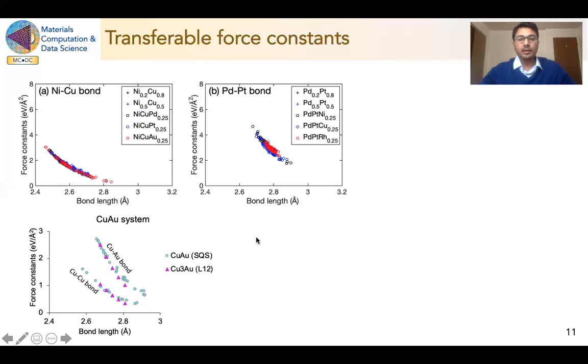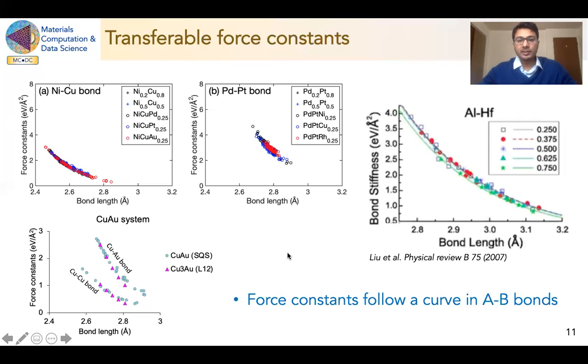Similarly, if we compare the force constants in ordered versus random alloys, again the force constants follow the same curve. As you can see in these two types of bonds, the copper-gold bond and the copper-copper bond in the copper-gold system, the force constants follow the same curve. It doesn't matter whether they are present in the random alloy or in the L12 ordered alloy. Similar observations have been reported in the literature also. Just for example, this is for the aluminium-hafnium system, and the force constants of aluminium-hafnium follow the same curve, although different compositions are considered in this study. So in general, we have observed that the force constants are transferable to different chemical environments.